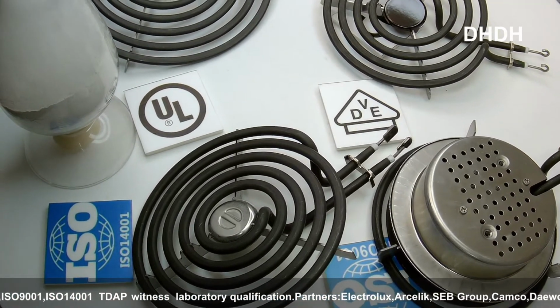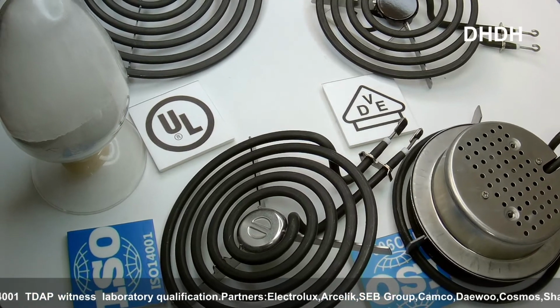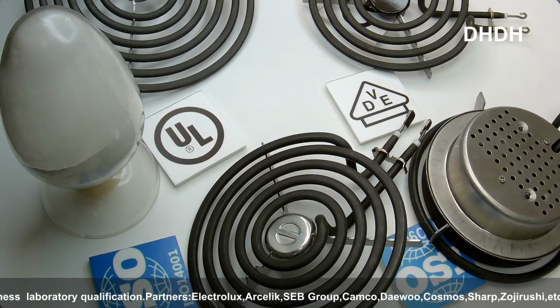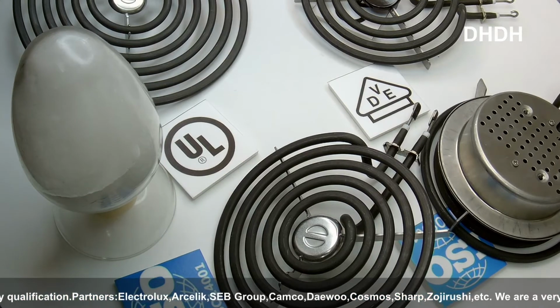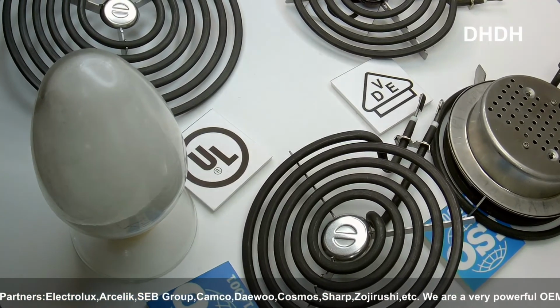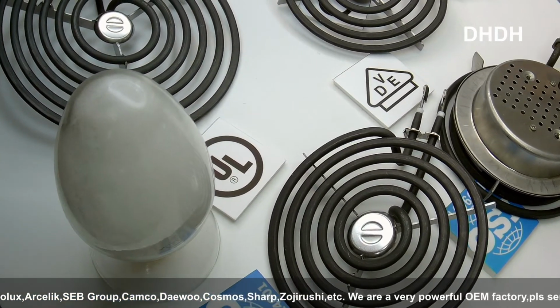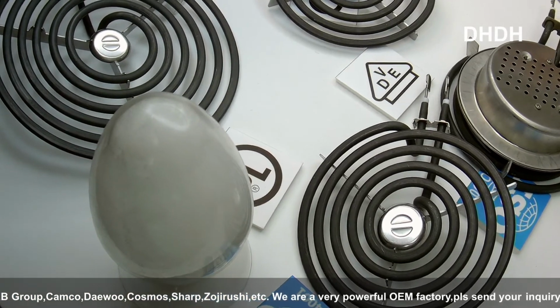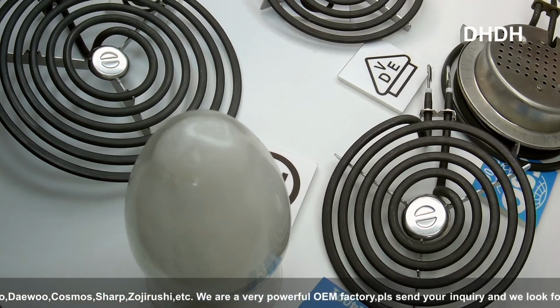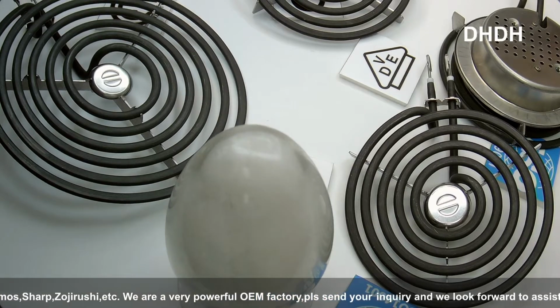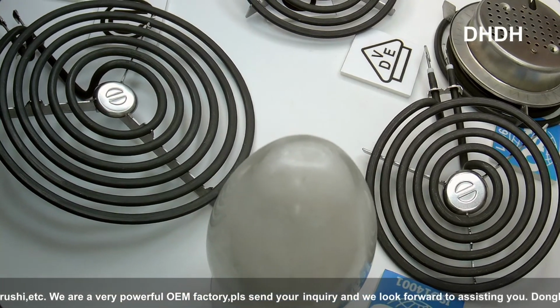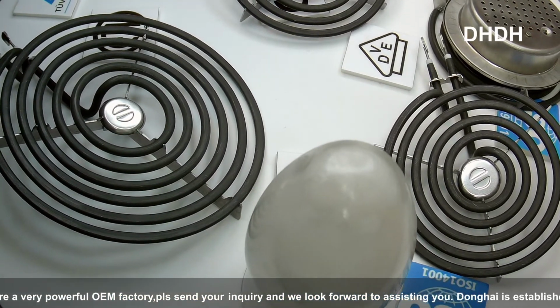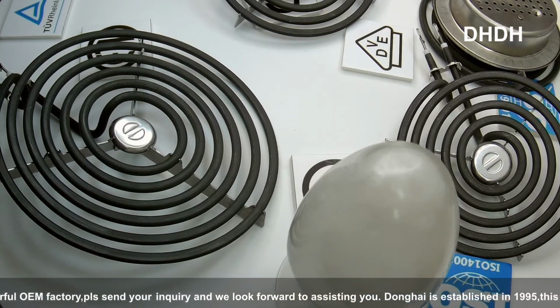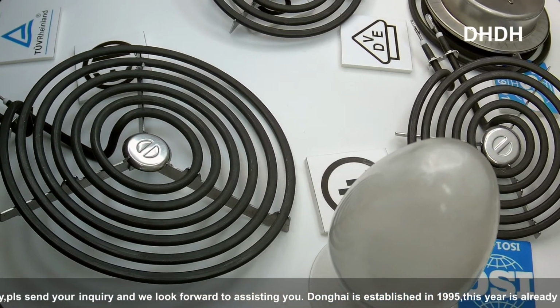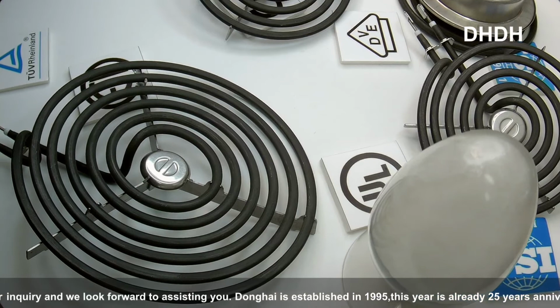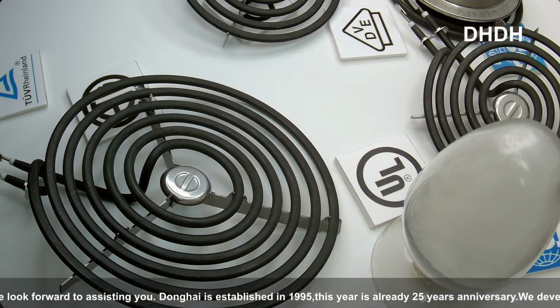Yes, just now you mentioned the raw material used in the tube. As you know, the price for different MGO powder grades is quite different. For some manufacturers, in order to save cost, they will use lower grade MGO containing silicone oil to make coil heaters, which may be dangerous. When the coil heater heats up, the silicone oil runs in the tube, and when the silicon gathers together, it is very easily carbonized, so the tube will burst easily, which is very dangerous.